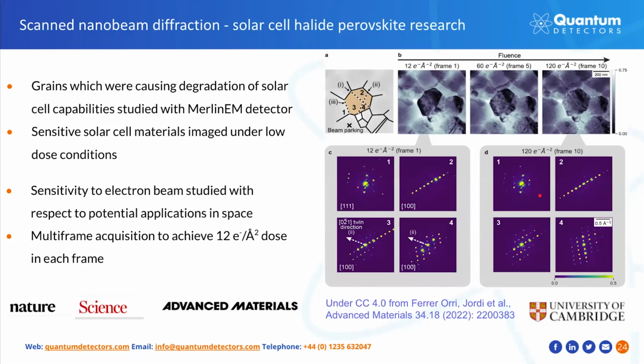As a last example of the data collected by MerlinEM, we show a study of degradation of the perovskite solar cell material, which is induced by the dose coming from the electron beam itself. The study was relating the dose the sample was exposed to in the microscope to the conditions it would have to survive if deployed on satellites in space. The sample was scanned 10 times, and each of the passes exposed the sample to 12 electrons per angstrom squared, giving the overall dose of 120 electrons per angstrom squared. Because of the lack of readout noise in MerlinEM, we can now split acquisitions into multiple passes and see the dynamic development of the sample without additional noise, and hence expand what's possible in electron microscopy.